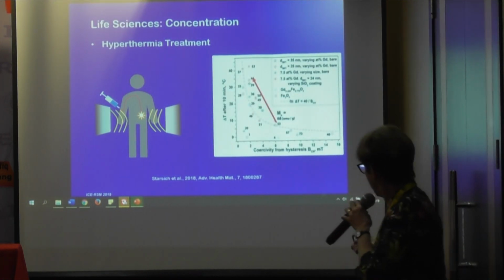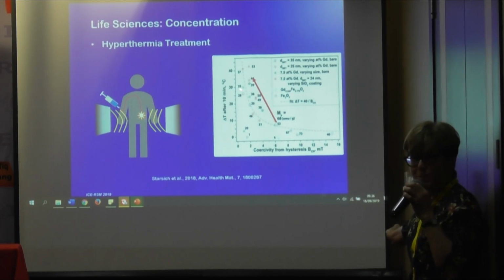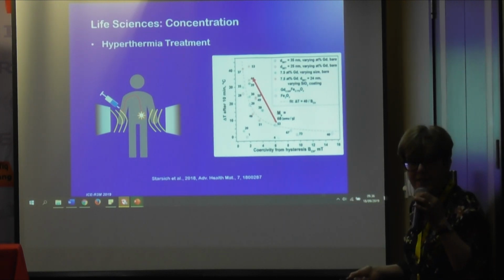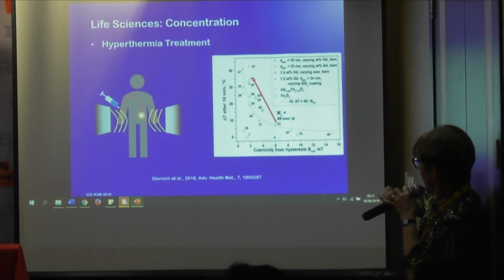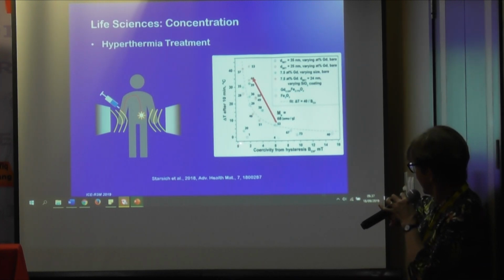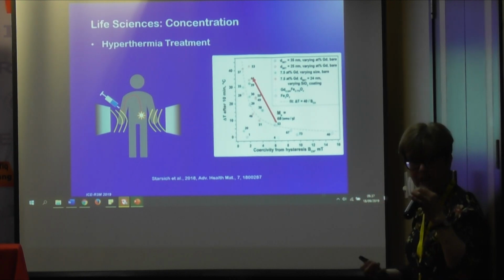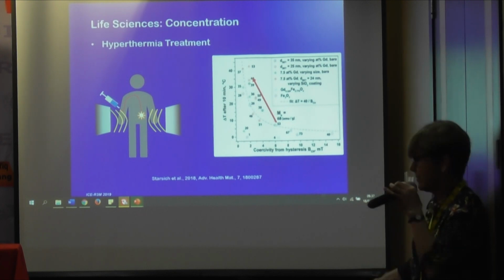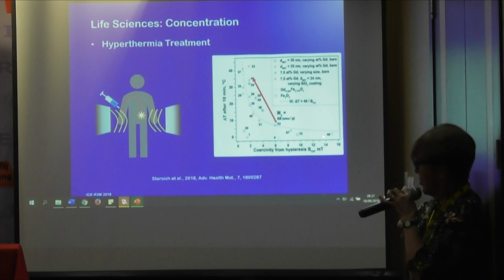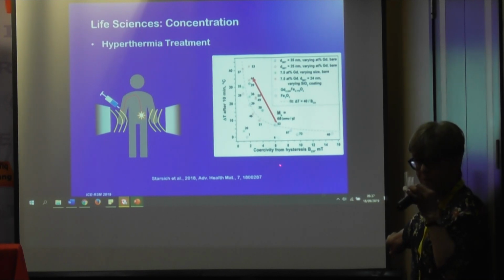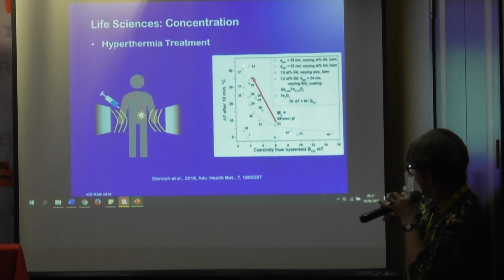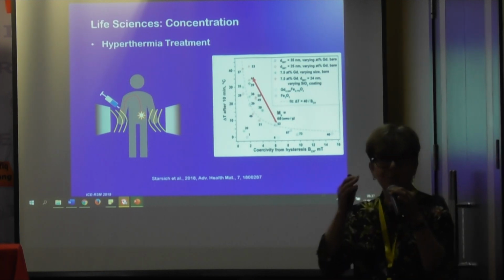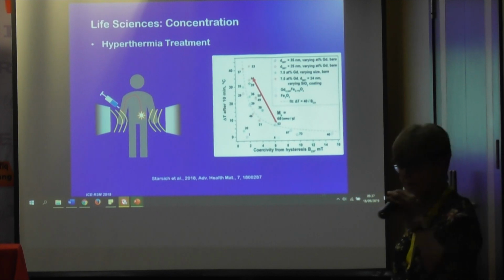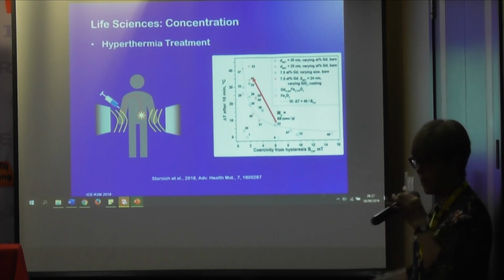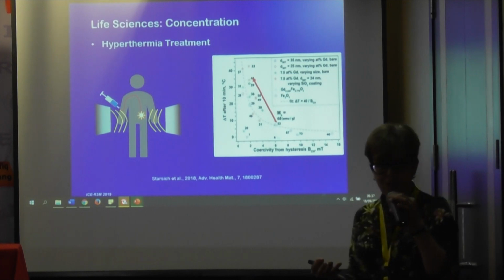It's a little bit low, but what you can see here is the student was making materials with many different grain sizes, many different compositions. What you see on this axis is the change in temperature. So he could get anywhere from almost no change up to a 40 degrees Celsius change in the nanoparticle itself. And what he found is if you plotted against the coercivity measured from a hysteresis loop, the highest heating was coming from the ones with the lowest coercivity in most cases. But there were also particles here with low coercivity that did not generate much heat.